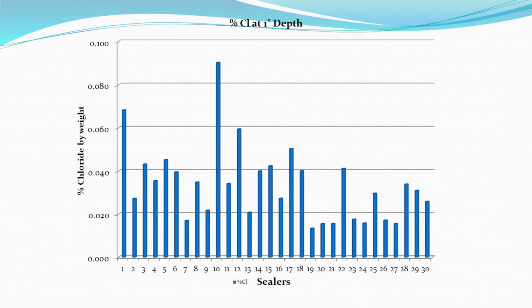This is the same set of data, only at 1 inch depth. Again, you have a very limited number of products that are staying below the 0.03 threshold, while the lowest performers are still nearing or above 0.01, nearing 0.02 weight percent in 90 days at 1 inch deep.